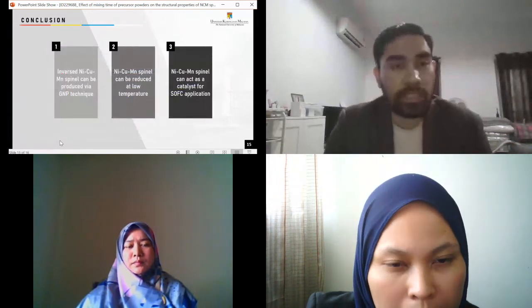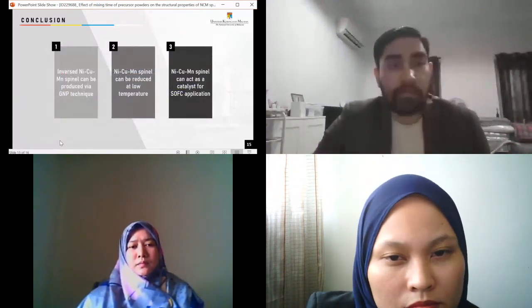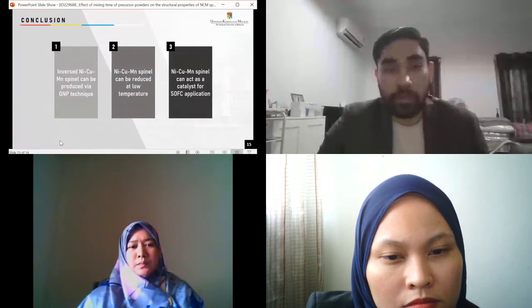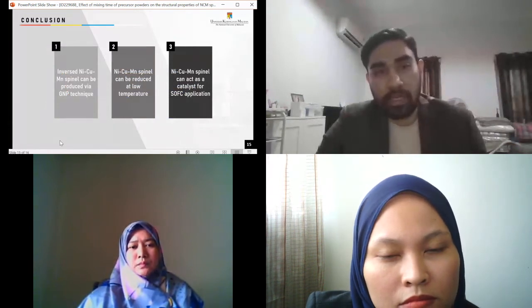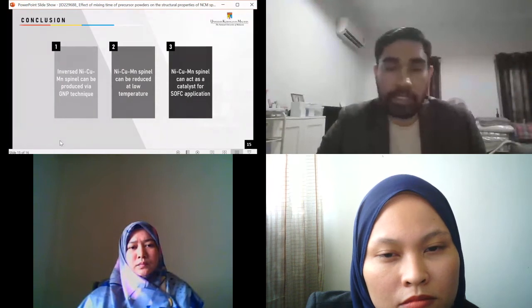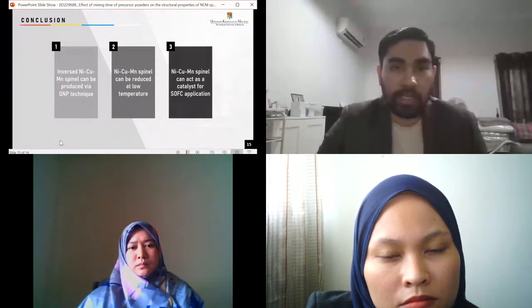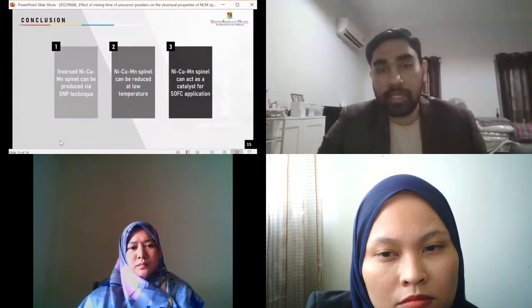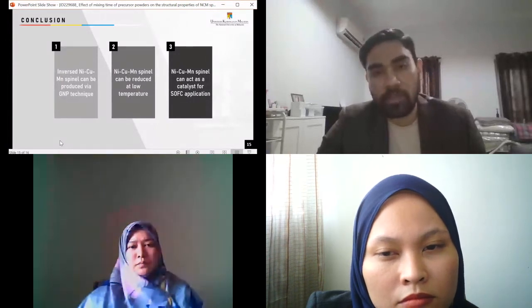As a conclusion, the first one, the inverse nickel copper manganese spinel can be produced via the GNP technique, where the spinel can be reduced at a very low temperature compared to previous studies, and it is expected that this spinel can act as a catalyst for solid oxide fuel cell application.